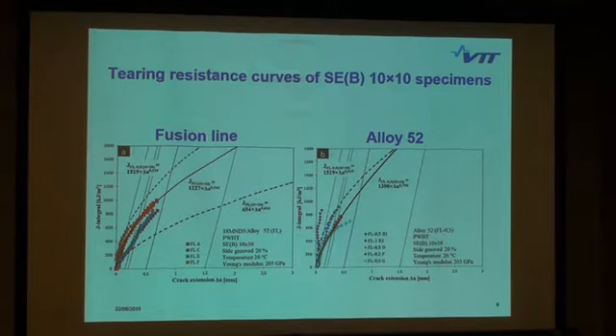And now when these fusion line results of the 10 times 10 specimens are compared to the 10 times 20 specimens, so we are at the fusion line, close to the boundary, you see that these results yield higher tearing resistance.